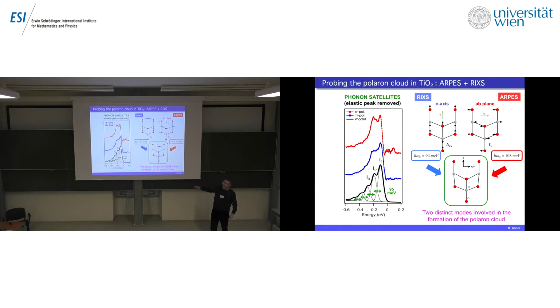I removed the main peak, zero energy loss, and what remains is the satellites. So you have a satellite structure, like in the ARPES experiment. These two spectra are for different conditions, for different polarization of the light, but essentially one has the same progression of vibrational states. The only difference with the photoemission is that the distance between two excitations is not 108 millielectronvolts, it's 94 or 95 millielectronvolts. And actually, together with the selection rules for the polarization, this tells us that it's not the same phonon mode. The mode that we saw in photoemission was in the ab plane of the material. This one here is another known phonon mode, which goes along the c-axis.